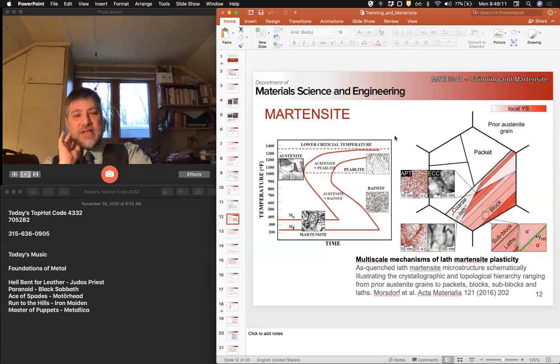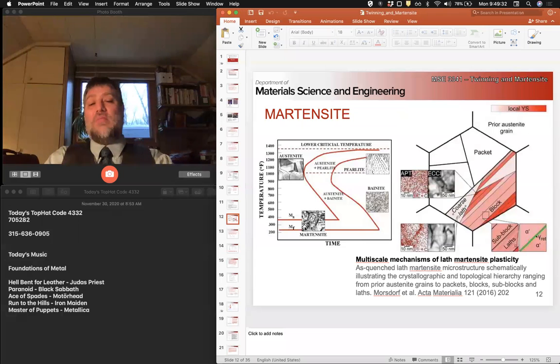But martensite is very similar to twinning in the sense that it's a shear transformation. But in this case, we're going from one crystal structure to another. In steel, we're going from austenite, which is FCC, to body-centered tetragonal martensite, which has a higher carbon content than the BCC ferrite, right? And martensite is athermal, meaning it's not thermally activated, right?